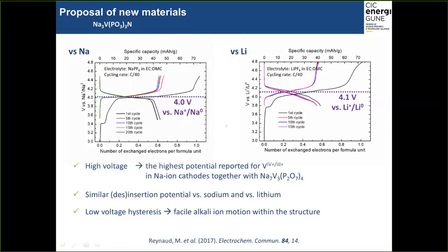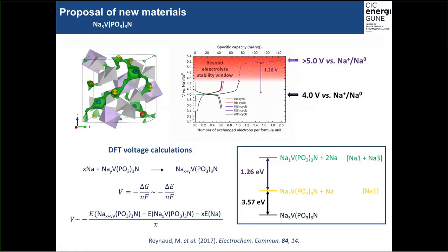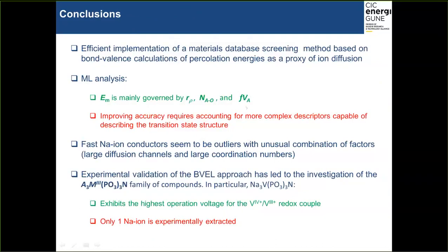The redox activity of the vanadium 3+/4+ couple appears around 4 volts versus sodium and 4.1 versus lithium. This is one of the highest potentials reported for vanadium 3+/4+ in sodium ion cathodes. And in both cases, there is a low voltage hysteresis, as you can see here, which supports the prediction of fast sodium ion mobility within this structure. Unfortunately, we can only extract one sodium per formula unit. The extraction of more than one sodium cation is beyond the voltage stability window of known electrolytes, as predicted here by DFT calculations.